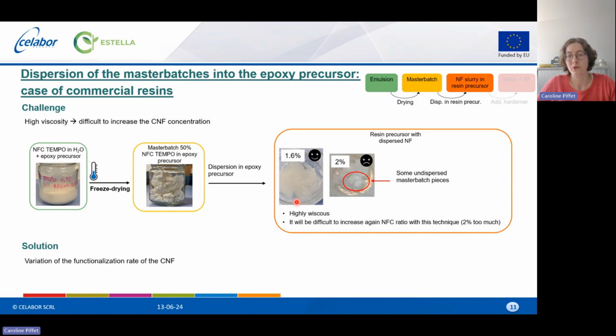So it is not a lot of fibers. And you see that when we try to increase just a little bit up to 2%, it is already too much. The media is very viscous. And we have still some master batch pieces not very properly dispersed. So we decided to vary the functionalization rate of the cellulose nanofibers to see if this strategy could help us to increase the dispersion of the nanofibers.